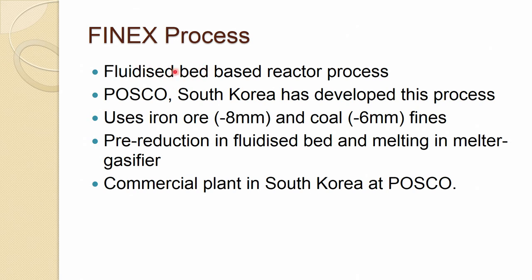So, the size of this ore would be low. POSCO, the South Korean steel company, actually developed this process. Essentially what they did, they studied the COREX process, they bought a COREX plant and modified that process and introduced the fluidized bed, and that is how they came up with the FINEX process. So, it uses iron ore of less than 8 millimeter. So, it can use the fines, and in the same way coal fines also.